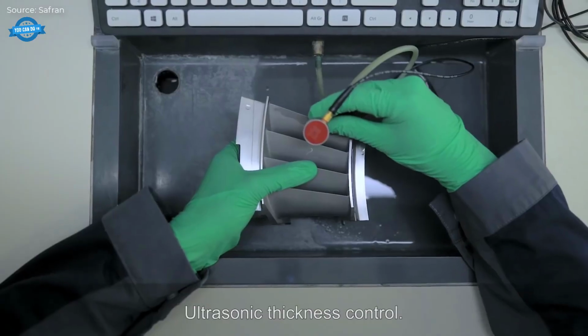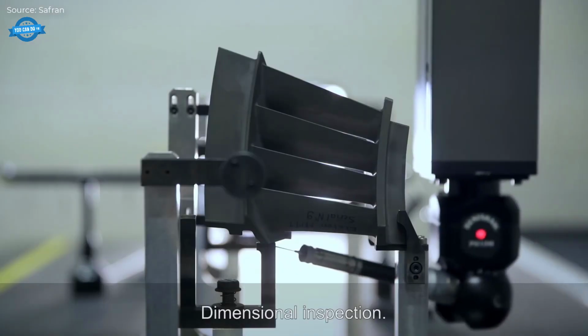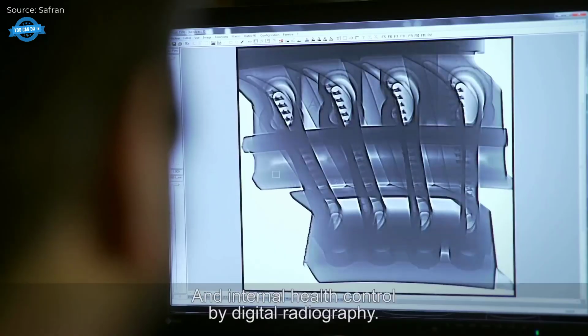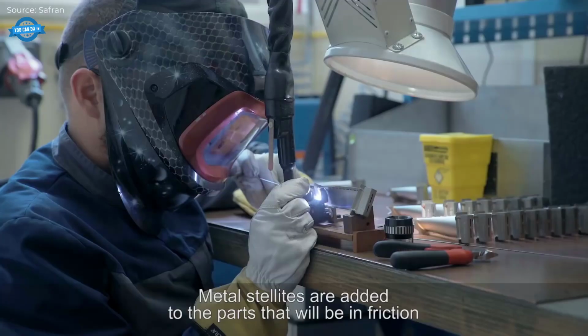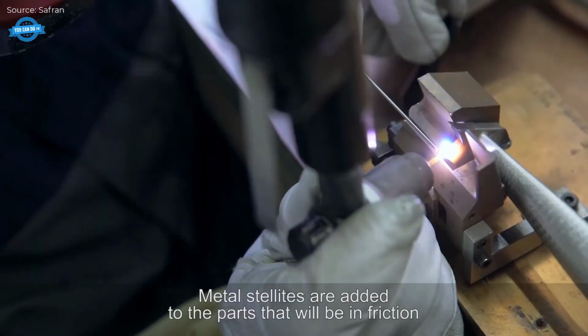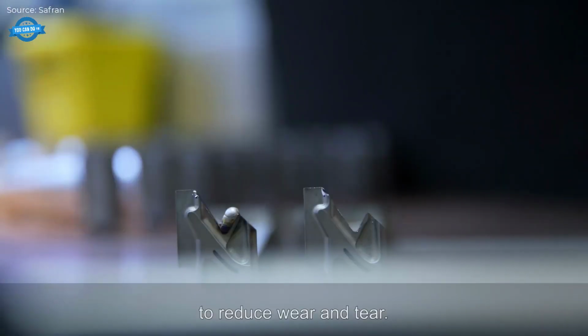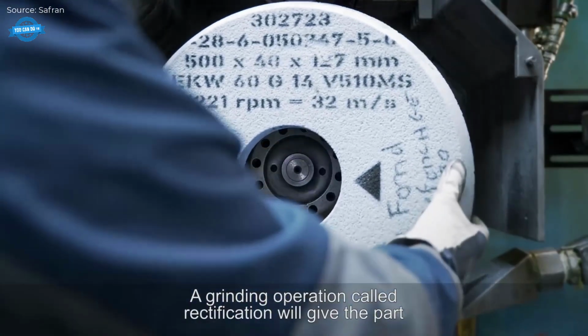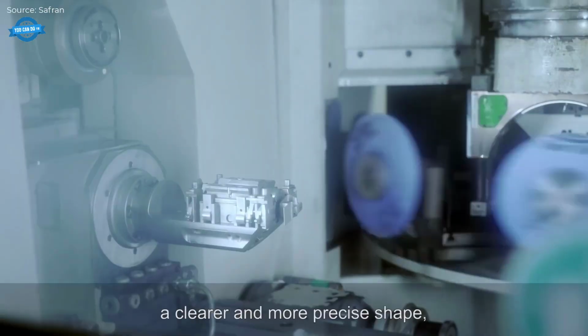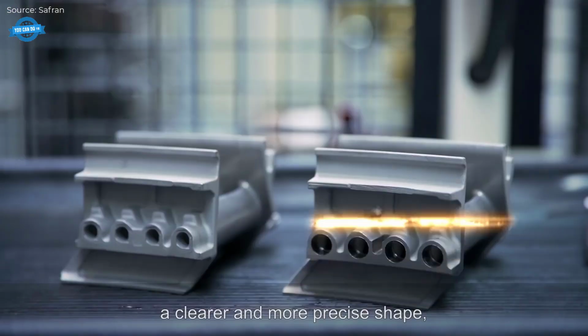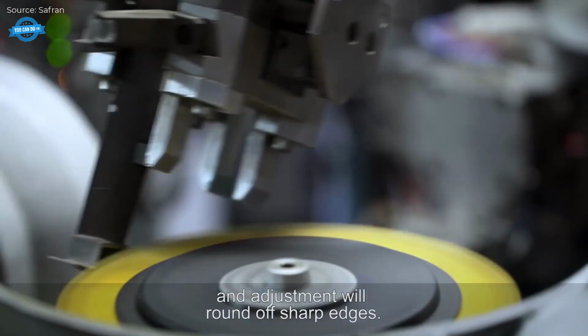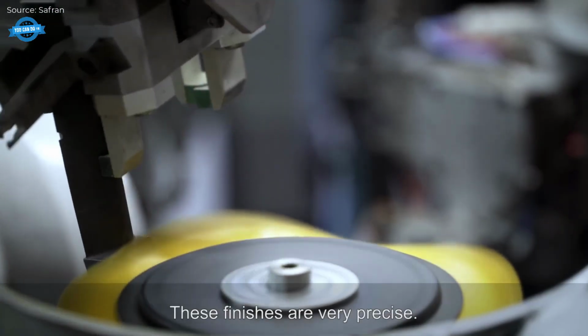One of the key finishing operations is rectification, where grinding refines the part's dimensions and smooths rough edges. For turbine blades that experience friction during operation, a metal alloy called stellite is applied to areas prone to wear. Precision 3D measuring machines then conduct up to 150 measurements per blade to ensure conformity with design specifications.